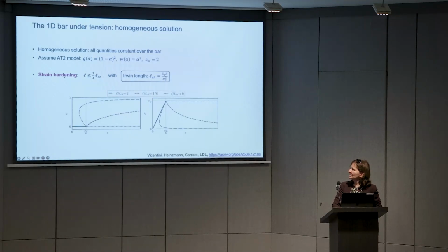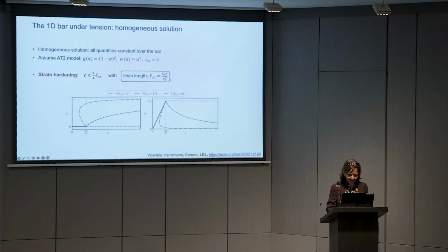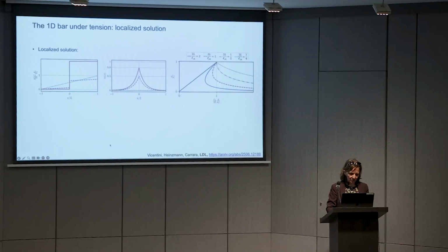So the strain hardening condition, interestingly, gives us a condition on the length scale. To satisfy strain hardening and have no snapbacks at local level, we need the length scale to be smaller than the cohesive length scale of the material, which anybody working on cohesive models for fracture may have seen. This is the so-called Irwin length, and depends on the fracture toughness, elastic modulus, and the tensile strength of the material. And you can also show that when you reach the peak of the stress, even for short bars, the solution is unstable. This is also interesting.